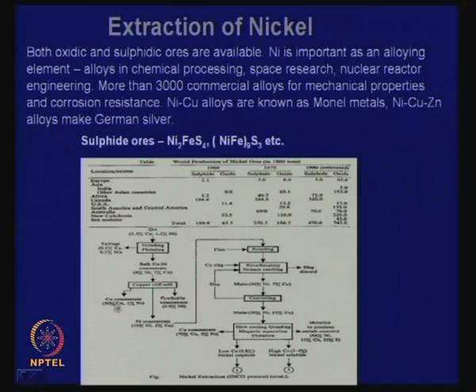Then they separate copper concentrate and pyrrhotite concentrate. We will get a concentrate with 30% copper and 1% nickel, and we will get a main nickel concentrate which will have 10% nickel, 2% copper. This becomes now the starting point. It will now undergo pyrometallurgical processing, very much like copper sulfide processing, where we will go through a matte route, a route that will involve sulfides. So, this nickel sulfide concentrate, which would have 10% nickel and 2% copper, will go for roasting, reverberatory furnace smelting, just like in the case of copper. There will be slag discard, and this will now produce a matte.